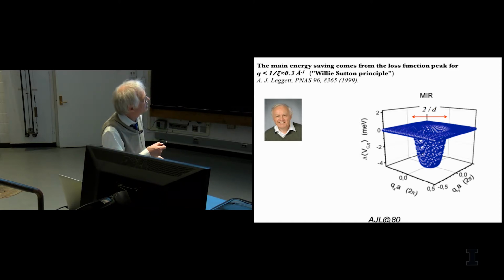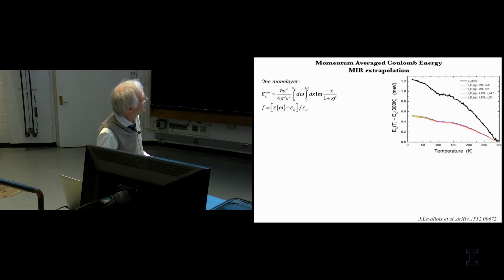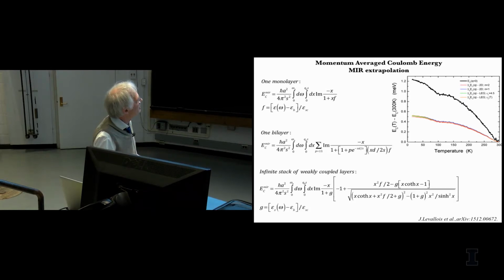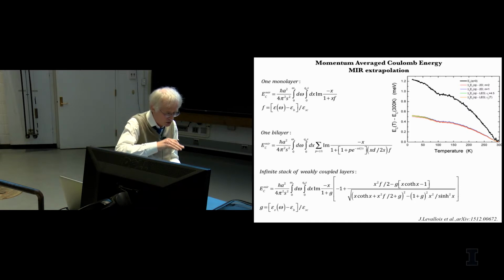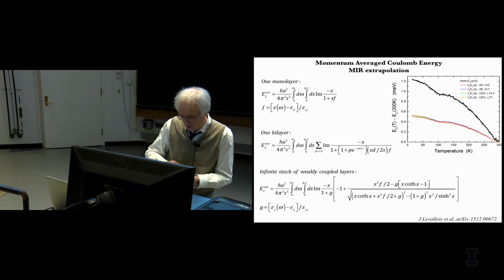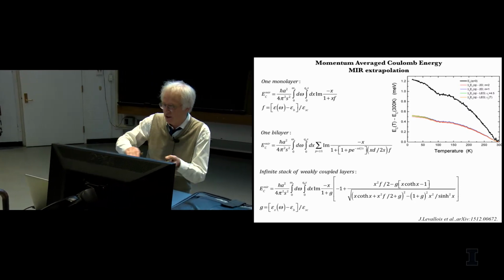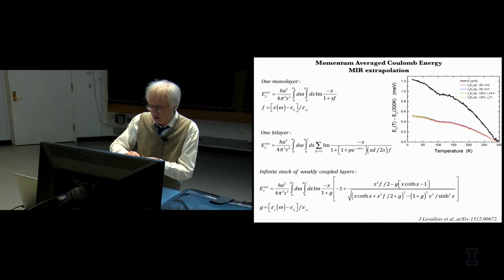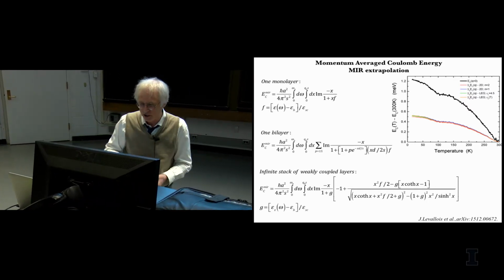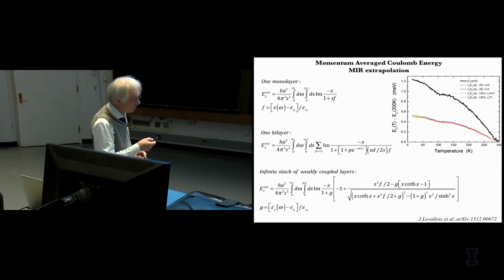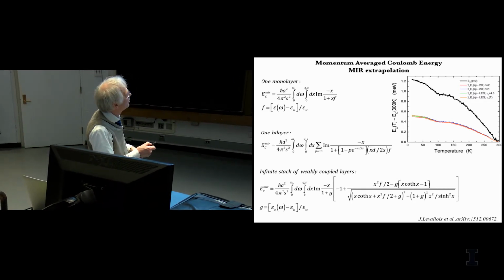And so you just have to integrate over that number, and you would get the right value. There are different ways of doing that, but time is running fast, and I should go. Actually, we tested different ways of doing that extrapolation, making different kinds of assumptions about whether you have a single layer only, or a stack of layers, or a stack of bilayers, and so on and so forth. And all these different extrapolation schemes give the same prediction, essentially. These are the different colors.